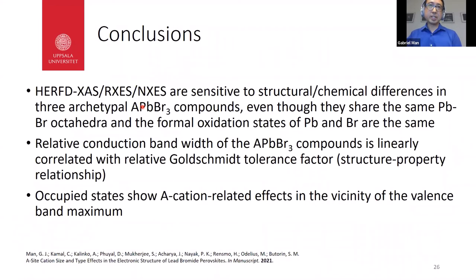So I'm just going to wrap up this first sub-talk with some conclusions. First, HERFD XAS, RIXS, and normal X-ray emission are very sensitive to structural and chemical differences in three archetypal lead bromide compounds, even though they share the same lead bromide octahedra, and the formal oxidation states of lead and bromine are the same. The second conclusion is that the relative conduction bandwidth of the lead bromide compounds, and possibly all halide perovskite compounds, is linearly correlated with the relative Goldschmidt tolerance factor. And the third is that the occupied states show A-cation related effects, mostly in the vicinity of the valence band maximum.